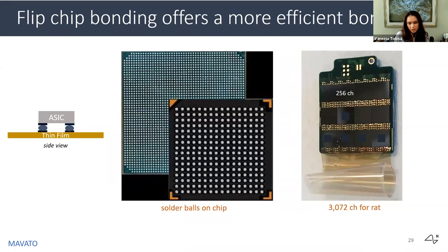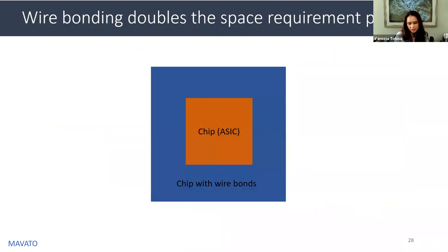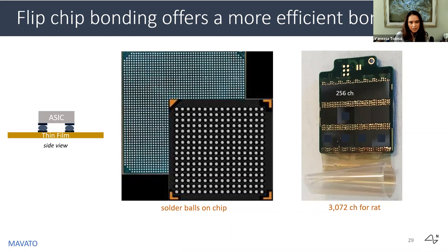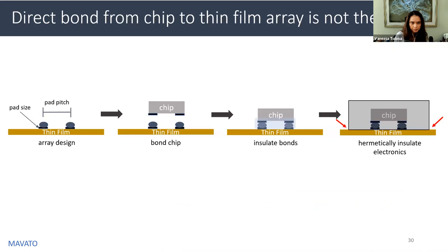So that's what we actually put in action in this next version of our device. Here we had a 256 channel model, and then we eventually got to 3000 channels using this method where we just really densely packed our chips. And that was what was used for the rat studies that I showed earlier. So this is okay for animal studies, but it doesn't work well for long-term implantable human devices. The main reason being that it's difficult to get a hermetic seal around the electronics.